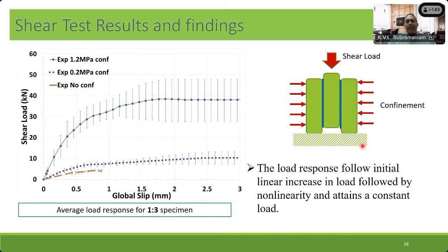Now, this is the typical result that we get for the triplet test. What are we measuring here? We are measuring the shear load that I'm applying on the middle brick and the slip that happens in this brick. That's essentially what we're measuring. Initially, when the mortar is intact, there'll be no slip. As this mortar interface fails, this interface also fails, and the middle brick will start slipping relative to the other two bricks. Now, this is what the load versus global slip, or the slip of the middle brick, looks like for three levels of confinement. When I have no confinement, you get a shear load versus slip response that looks like this.